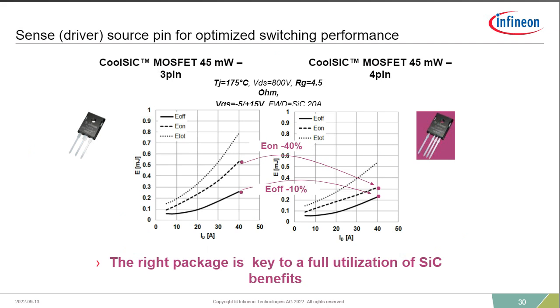We do have available 4-pin devices, as well as our TO263-7 devices have a Kelvin source pin, just like the 4-pin device here shown. And this helps reduce your E on by about 40% and your E off by about 10%. So if your application is driving the MOSFET at switching frequencies above 100 kilohertz, then we recommend the 4-pin in your application, and it will help you save overall losses in the application. And if you're very concerned about power density in your application and overall heat, you can also choose the 4-pin even at lower switching frequencies. But obviously there is some price adder for a 4-pin device over a 3-pin device.